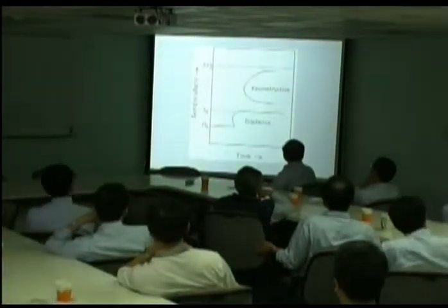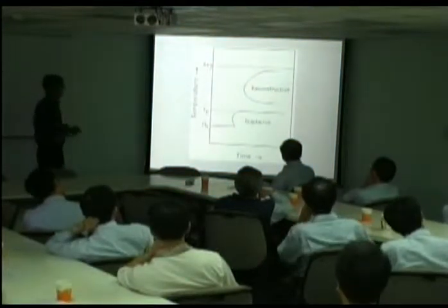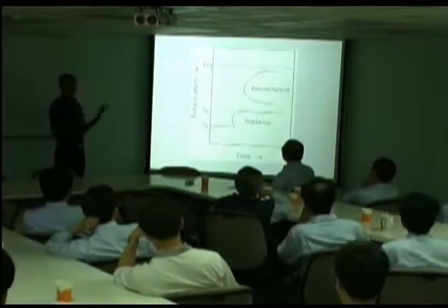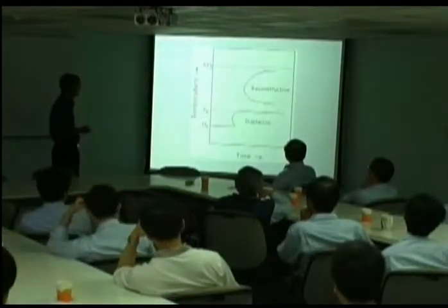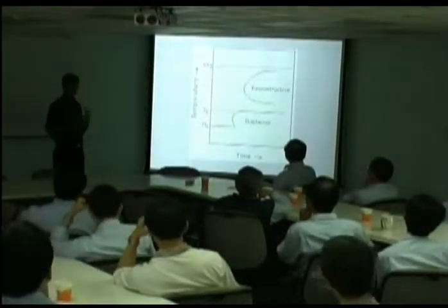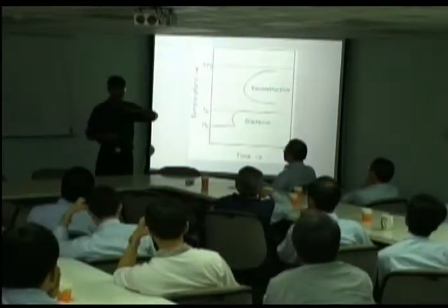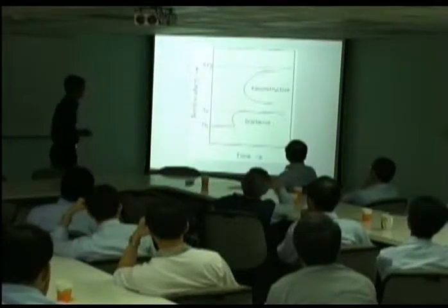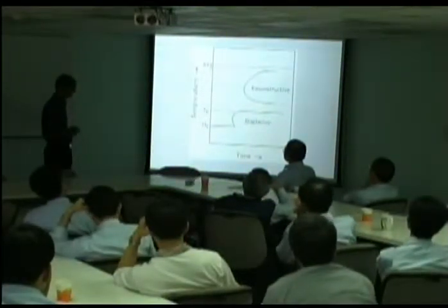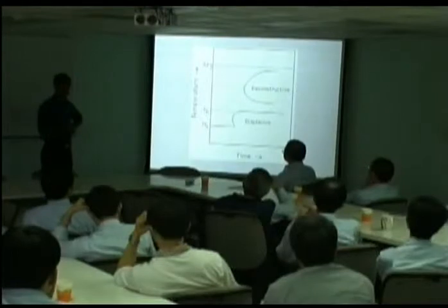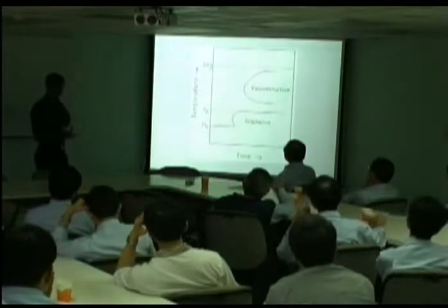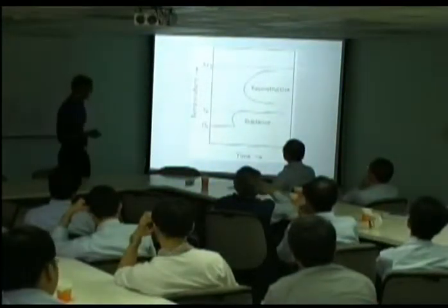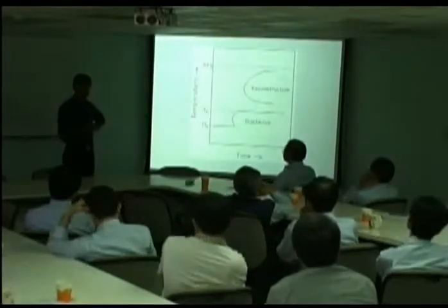Right, now this is a typical time temperature transformation diagram, where here is the C curve for allotriomorphic ferrite and pearlite, which are diffusional transformations, and this is the C curve for all the transformations where you see a shape change, a shear deformation. And these C curves are characterized by a flat top here, which has a temperature which I'll call T with a subscript H. So for every alloy, I can find two C curves and I can define this temperature TH. And I want to find out how much driving force I have available at this temperature TH.